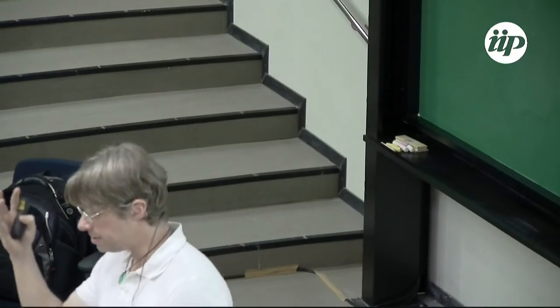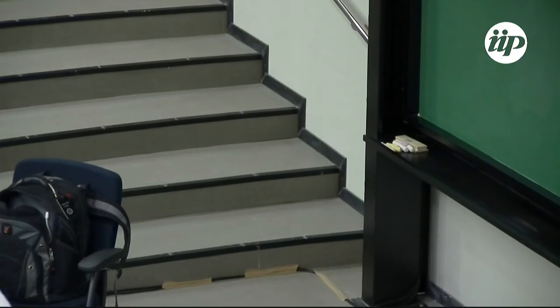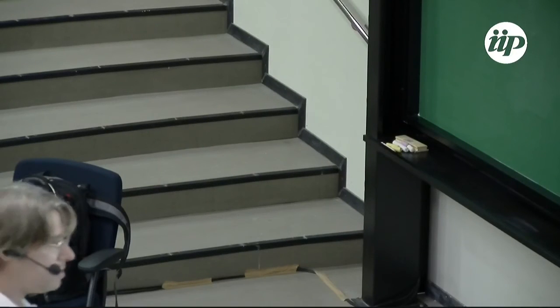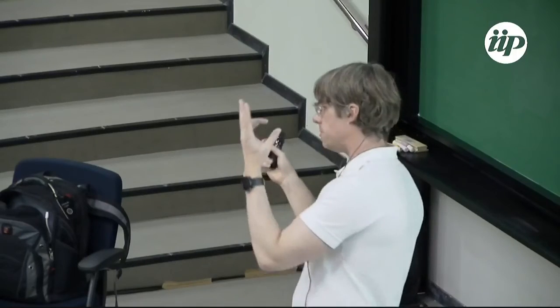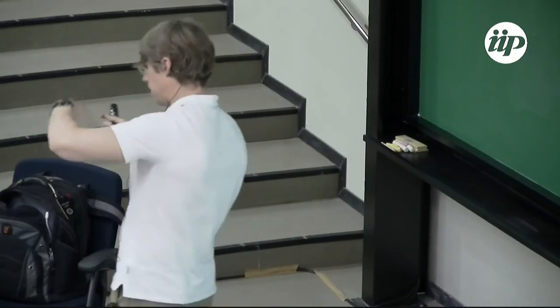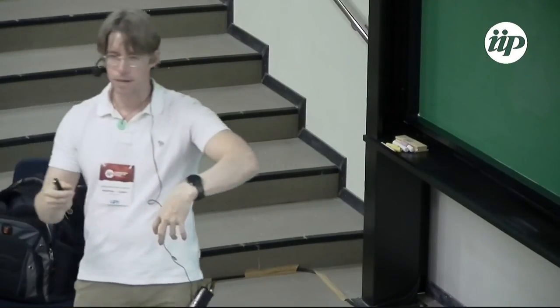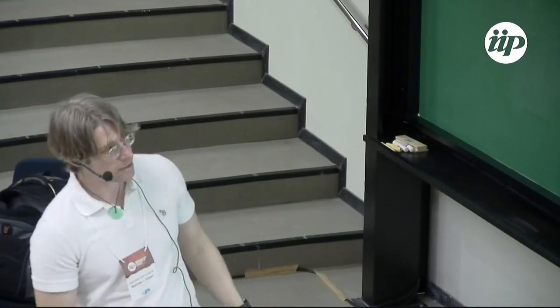So when we put this together, we had to do some tricks so that you can, sure enough, use this Hamiltonian, add in the Zeeman terms, and you can get a very messy-looking Hamiltonian. But if you want to be a little bit more elegant, then you can start doing some rotations. You can perform an SU(2) rotation on both the spin sector and the layer sector, so that in the real spin and the pseudo spin, you can get a hybridized basis as soon as you start making these rotations. What you get is a simpler Hamiltonian.